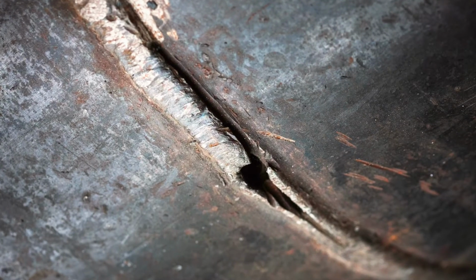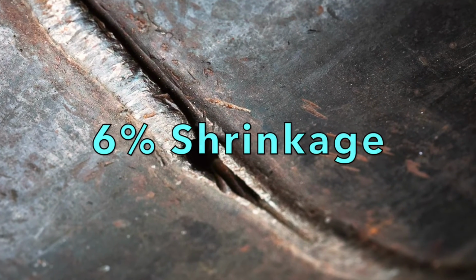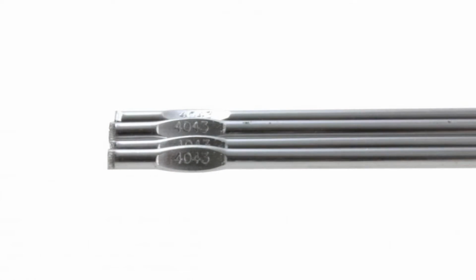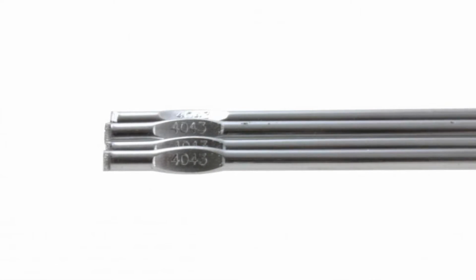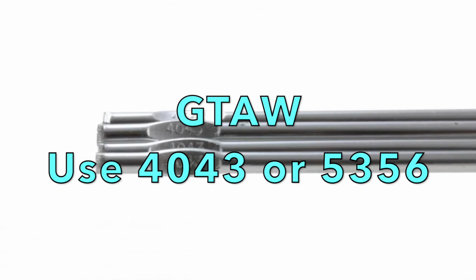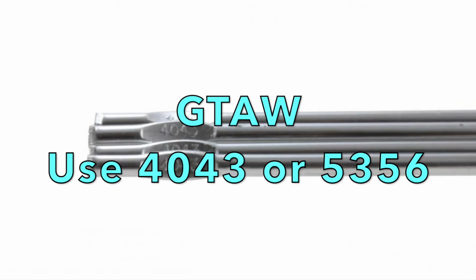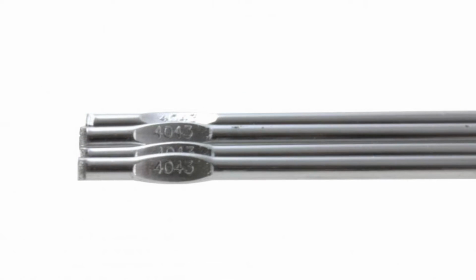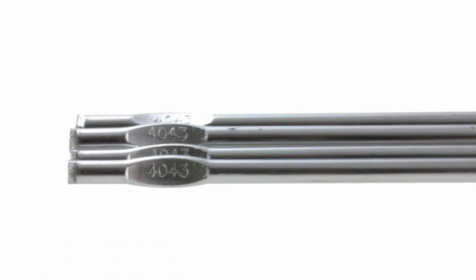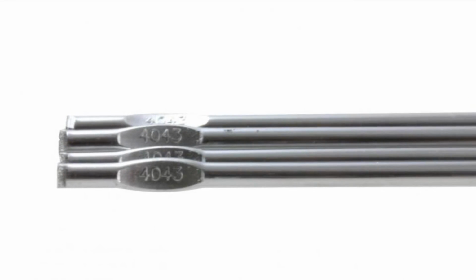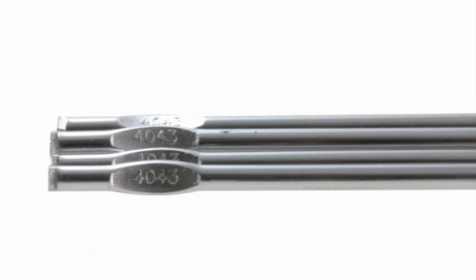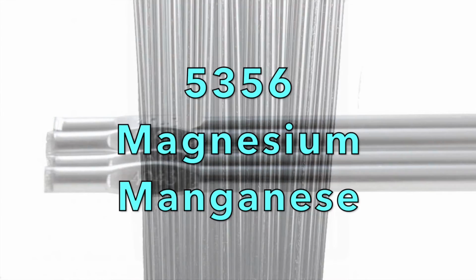Once the molten weld puddle has solidified, it will shrink approximately 6%, which can cause distortion or cracking of the weld. When gas tungsten arc, GTA welding, the most common electrodes used are 4043 and 5356. 4043 is a general use filler rod. It has a lower melting temperature, which helps with a free-flowing weld puddle.